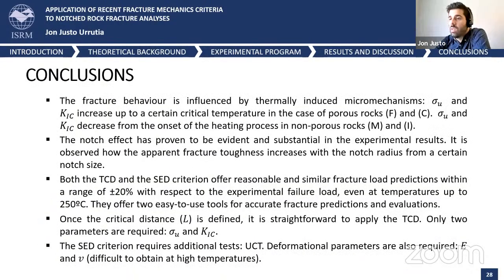And just to finish, I would like to highlight that the fracture behavior is influenced by thermally induced micromechanisms. We saw that both the tensile strength and the fracture toughness increase up to a certain critical temperature in the case of porous rocks, while they decrease from the onset of the heating process in the case of non-porous rocks. We also saw that the notch effect was evident and significant in the experimental results. It was observed how the apparent fracture toughness increases with the notch radius from a certain notch size.